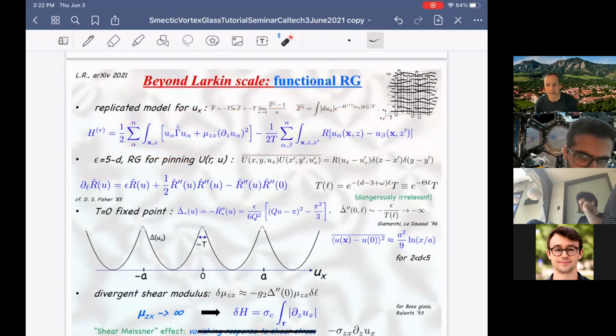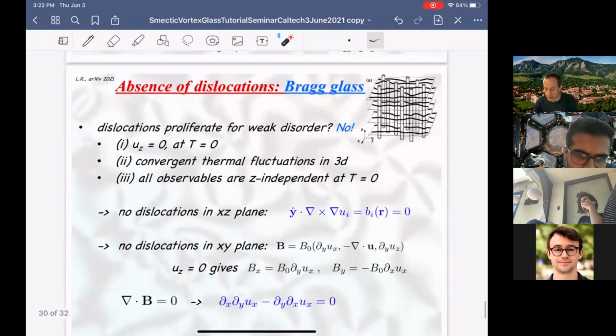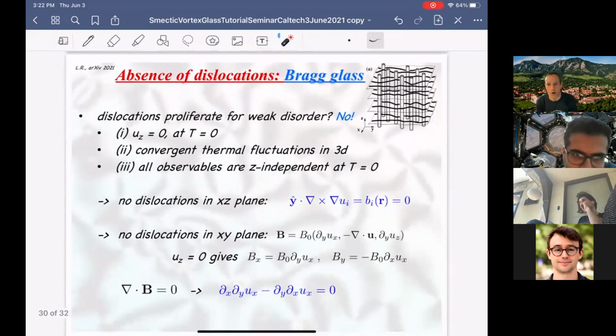But now I have to make some arguments about including topological defects, namely dislocations. And that's potentially infinitely harder, because now you have disorder, elasticity, and topological defects, singularities in the distortion field. So that's challenging. And that's what I said for ordinary vortex glasses. We believe in 3 dimensions, from simulations and real space RG by Daniel Fisher, that it is stable. There's a Bragg glass state.